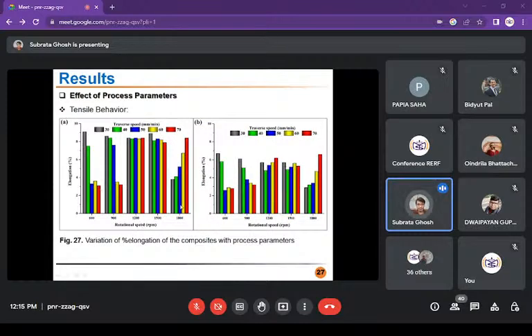And these are the elongations. Obviously we are following the same trend, but in the second pass the elongation is a little bit less, because in the first pass the material is a little bit more ductile. So ductility in the second pass is dropping. Think about the reinforcement materials: these are all ceramic materials, and ceramics are brittle materials. Brittle materials have low ductility, very simple. So in the second pass, because of the overall distribution of the particles, the overall ductility becomes less.